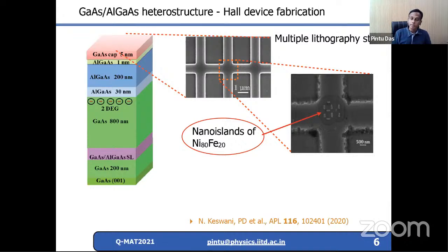So please remember that we are not measuring any magnetization. We are measuring the stray field coming out of the nanomagnets and reaching the two-dimensional electron gas, which is around 230 nanometer down the surface. And so what we are doing is measuring the Hall voltage due to the stray field, Hall voltage of the 2DEG. And from the Hall voltage, we are detecting the magnetic signal.